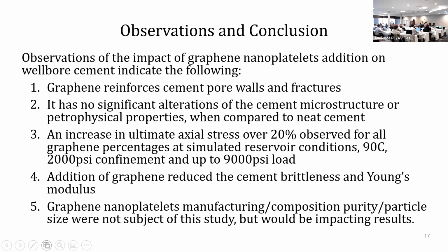We saw the increase in the axial stress at 90 C, 2000 PSI confinement, and I believe in some cases it went even above 9000 PSI. Addition of graphene did reduce brittleness. As for graphene nanoplatelets, there is really no uniform standard when you're purchasing these materials, so they do have some impurities, and we don't know how those impurities might be impacting cement hydration.